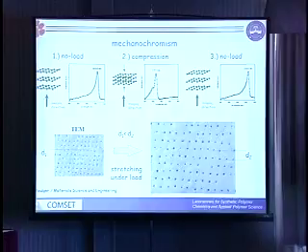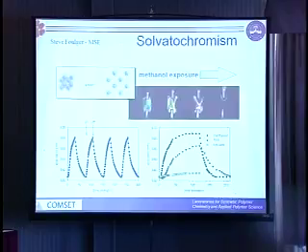And this is actually the TEM images of some of these composites, and you can see unbelievable order. This is just electrostatic ordering, and then dehydration, backfilling with another material, and cross-linking it. As you can see, there's defect areas here, but fascinating. It's just polystyrene, and you can get dramatic color changes in just 4% loading of polystyrene spheres in these cheap thermoset plastics. Of course, mechanochromism is just changing the d-spacing.